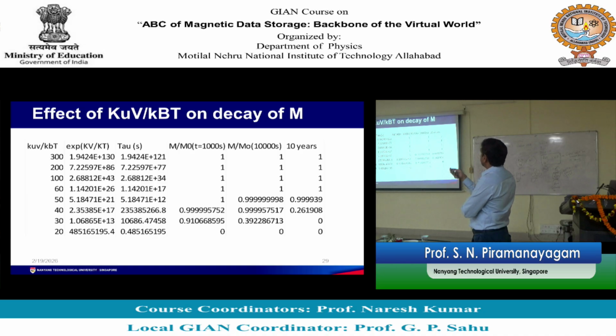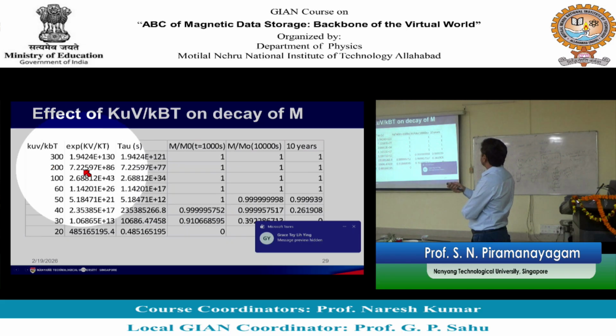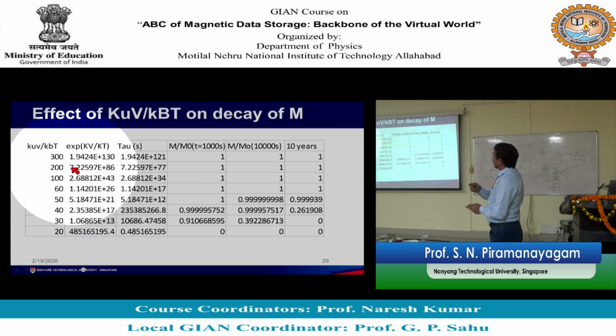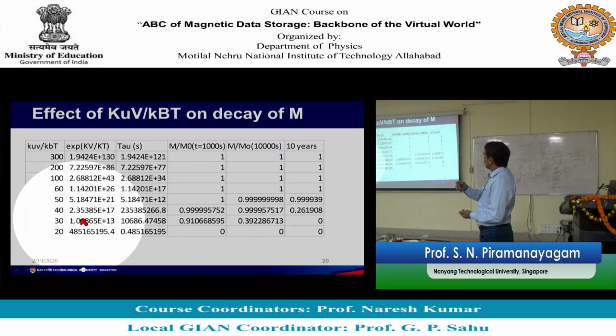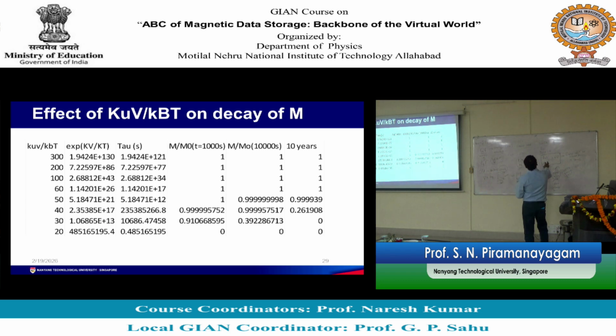So, here I prepared a table based on the KUV by KBT, showing how long it will take for the magnetization to reduce and so on. If you notice here, when the KUV by KBT is very large, say above 100, the magnetization does not change much even after 10 years, 60 also the same. But when you go below 60, the magnetization has dropped by a few percent, but when you go to 40 for example, the drop is very large. So, we do not want to go into this region, we want to keep the KUV by KBT larger than 60.